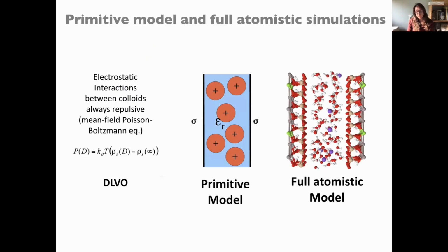So here I have put three different levels of descriptions. First, on the left, we have the DLVO, which is a theoretical description. On the other side, we have a full atomistic model where we can perform the potential of mean force calculations. And we have also a description in between, lighter than the atomistic model, where we have the primitive model. There we do the approximation as I was describing before, which is the whole particle is just a charged surface, and we can have the ions modeled as spherical particles with charge.